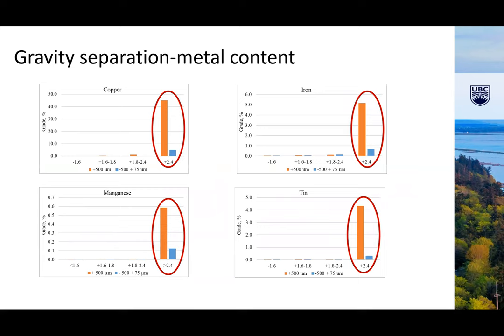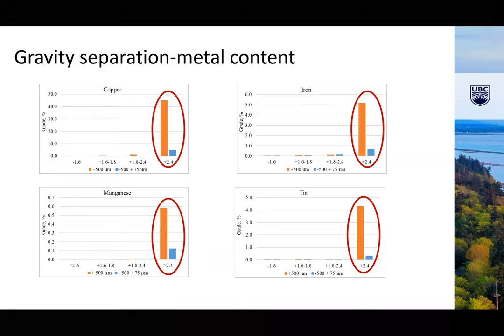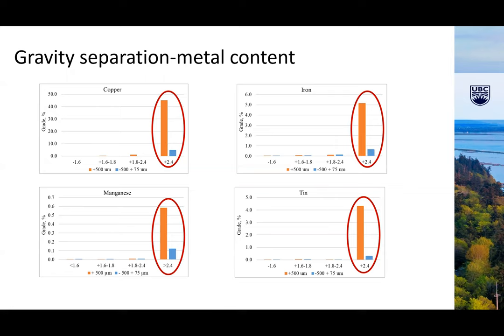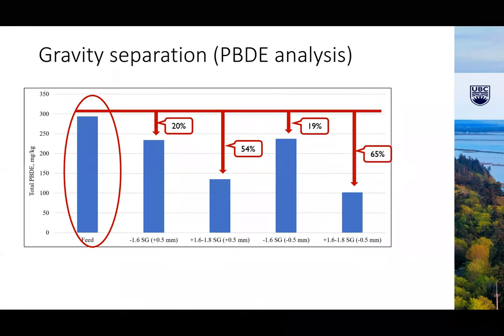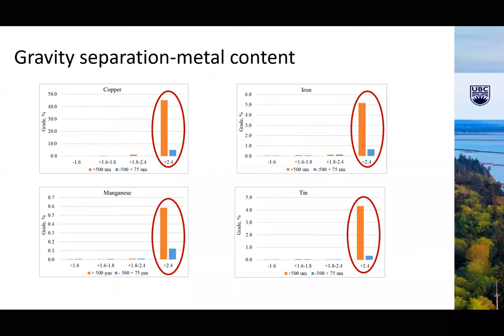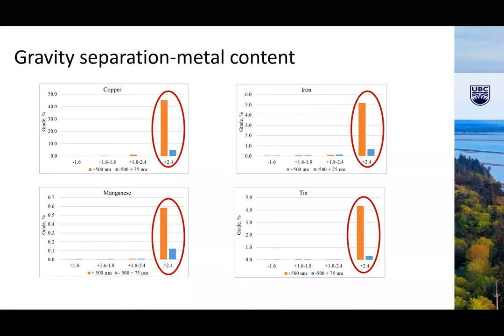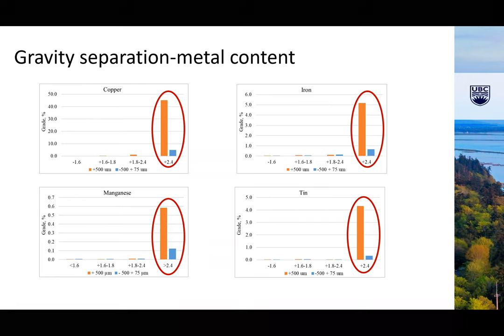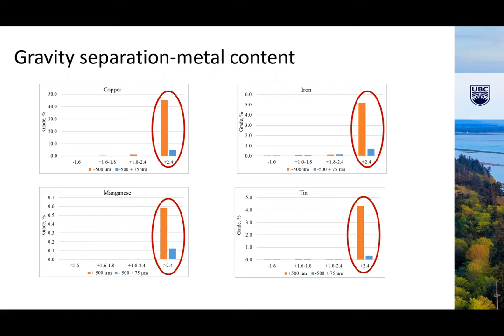So looking at the grade of metals, meaning percent of content of metals in various fractions, copper dominated in this heavy fraction, which is not surprising. There is a lot of copper in the printed circuit boards, and the actual percent of copper was close to what we produce at the mine, even though when we look at this copper value, 40% copper in this SG fraction. This fraction was only 2.5% mass, so not significant, but 40% copper, it means it's actually ready that it can be used for smelting purposes, for example. So not significant mass content, but yet in terms of value, probably could pay for the recycling of rest of the non-metal fraction.